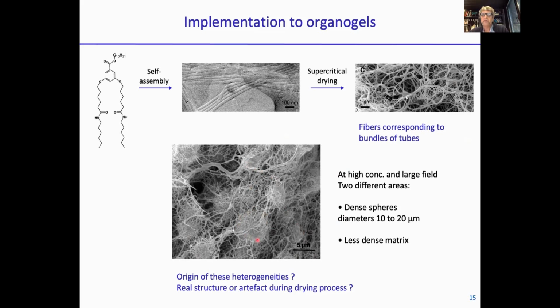We have these spherical objects that contain a high density of fibers, like here, here, or here. And we have looser areas that are less densely packed with fibers. So two areas, a denser one and a looser one. And what is the origin of these heterogeneities? Does it reflect the real, native structure, or is it an artifact of the drying process? Maybe pockets of solvent that were not well exchanged with the liquid CO2.